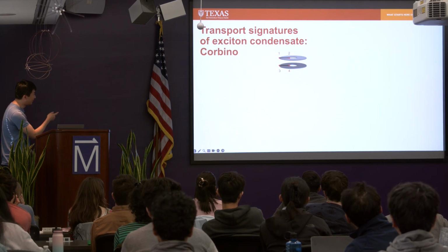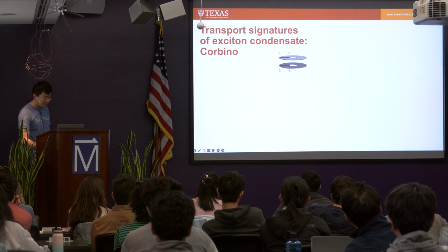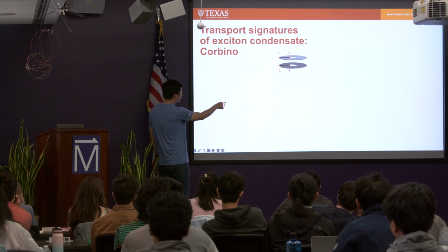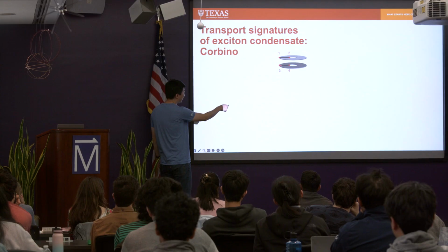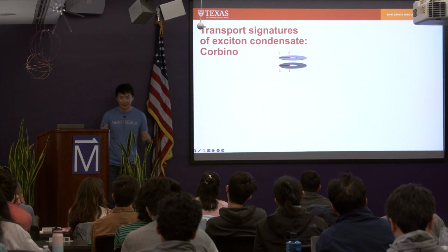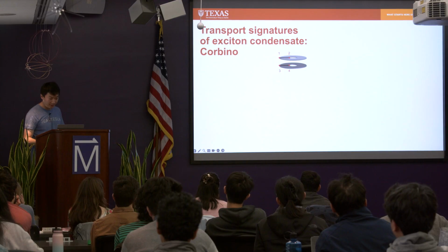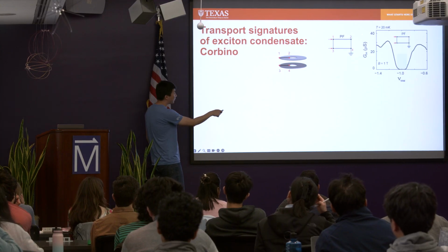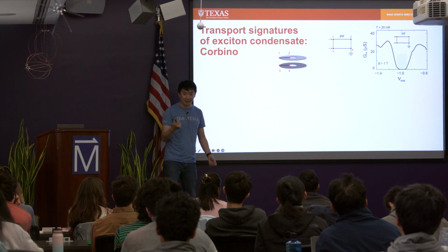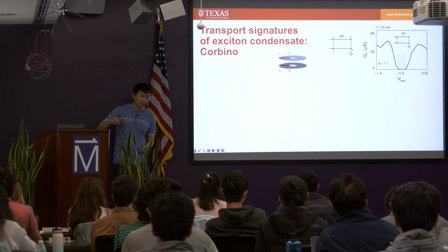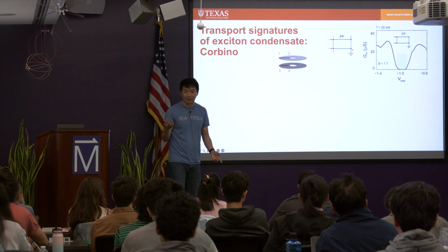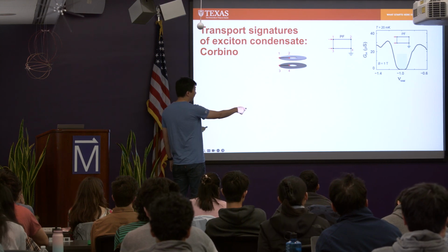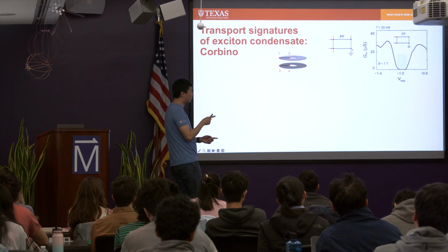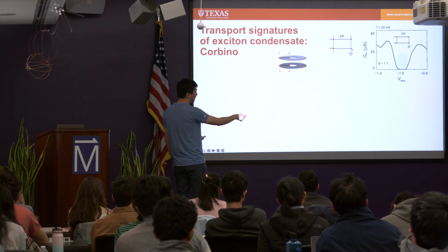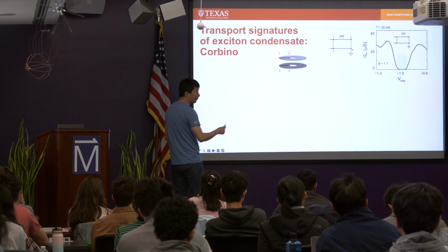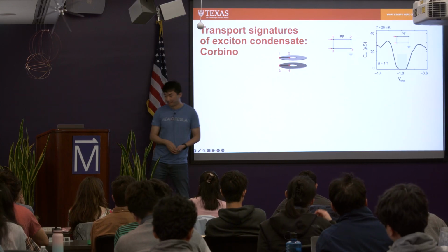Okay. So let me focus on the Corbino geometry, right? With the Corbino geometry, I identified the outer and inner edge of the top layer as 1 and 2, right? And 3 and 4 are those two of the bottom layer. And there are 3 different ways we can measure this, right? We can flow current in the same direction across top and bottom layer at this exciton condensate state. Because the exciton is overall charge neutral, when you try to flow current in the same direction, you will not flow, right? You will behave as an insulator. And so here I'm plotting conductance in this parallel flow configuration. So PF means parallel flow, as a function of total filling. At total filling of 1, meaning each layer is half filling, right? You see this insulator.